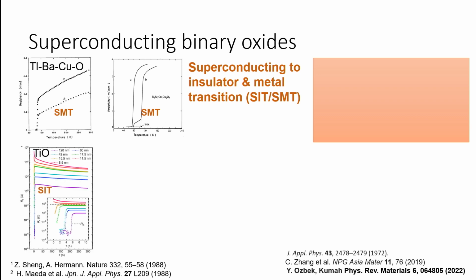Back in the late 60s and early 70s, there was a lot of work done on binary oxides, so niobium oxide, vanadium oxide, titanium oxide. And there were a few papers from that era which found that titanium monoxide, if you could stabilize titanium in a rock salt phase, you could actually get superconductivity a little bit below 2 Kelvin. So I think the TC in the bulk was around 1.8 Kelvin. Around 2019, there's a report from Zhang where they found that if you grew thin films of this titanium monoxide compound, you could get TC as high as 6 Kelvin. And there have been more recent papers which show that you can push this TC all the way up to about 11 Kelvin. I haven't seen the 11 Kelvin reproduced yet.